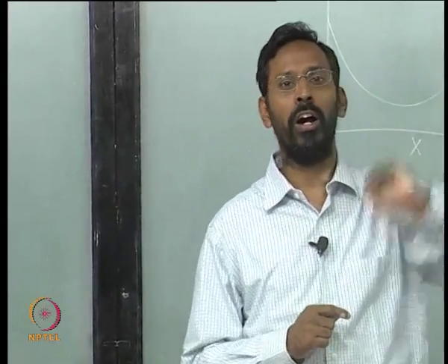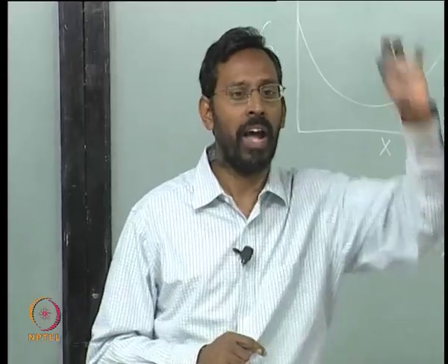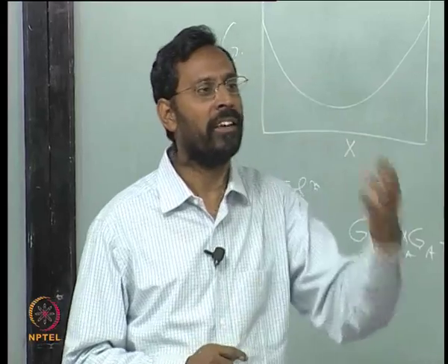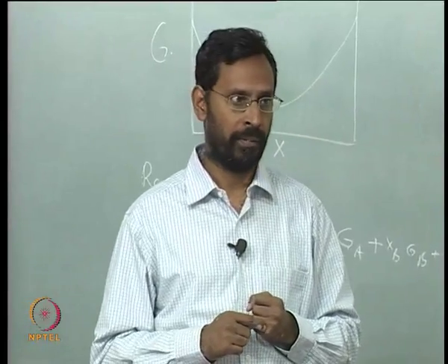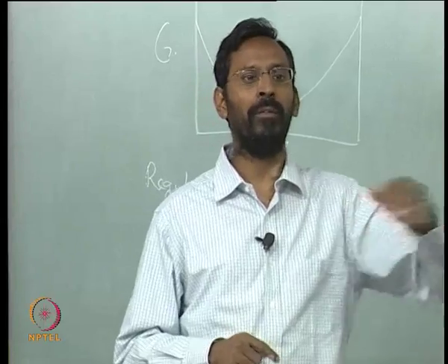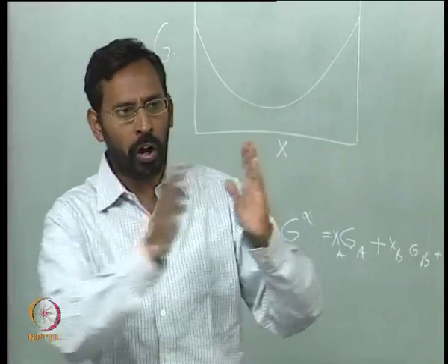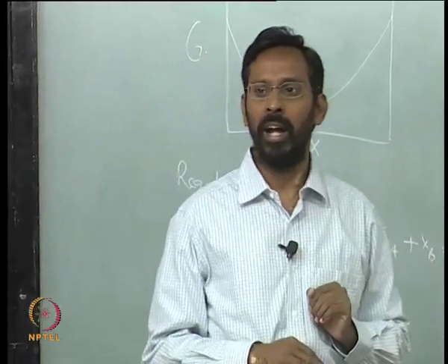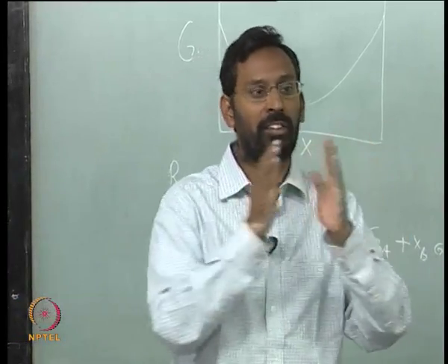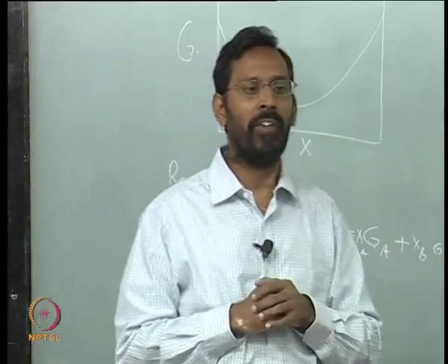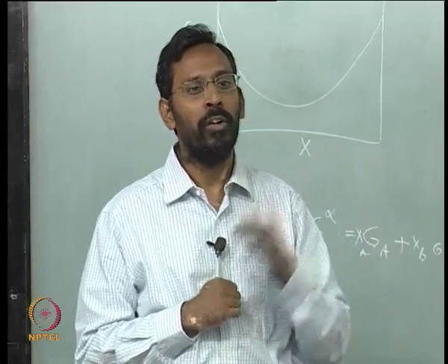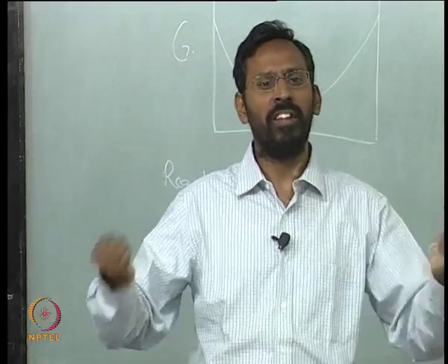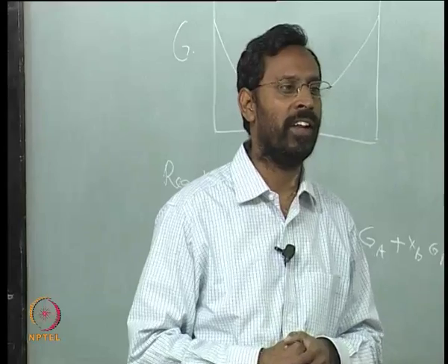That means those clusters at that particular composition have the lowest free energy or the highest bond energy, and as a result that cluster becomes stable there. And if for example I take an isomorphous system and choose all these possible combinations of 3:1, 1:1, 1:2, 1:3 and things like that, and try to calculate for each composition the value of this interaction, you would find that in an isomorphous system they are all equal at all compositions. That means such compounds cannot form in such a phase diagram.